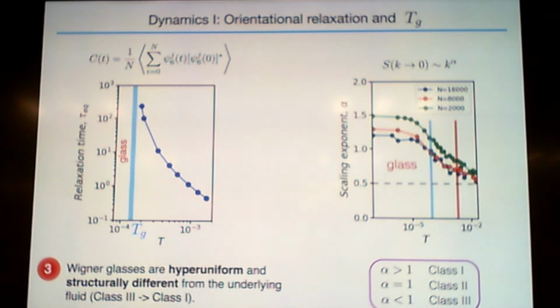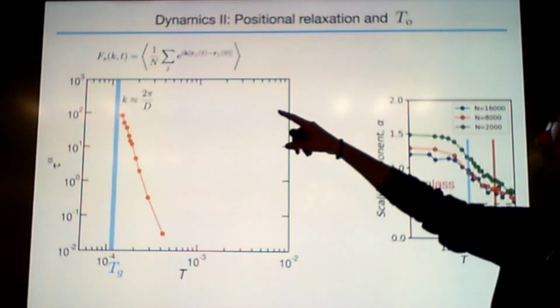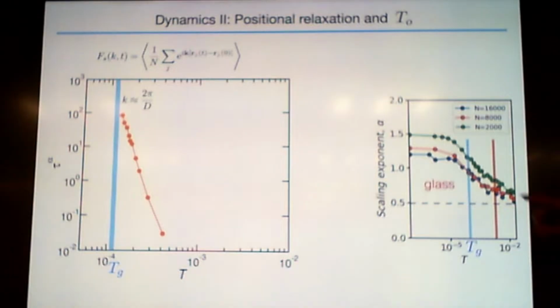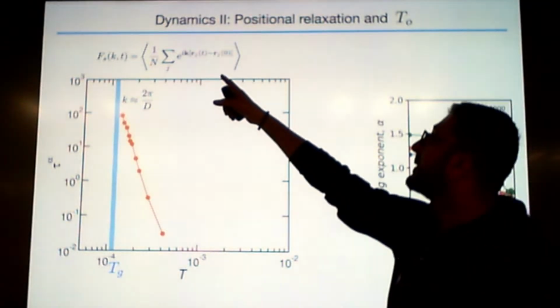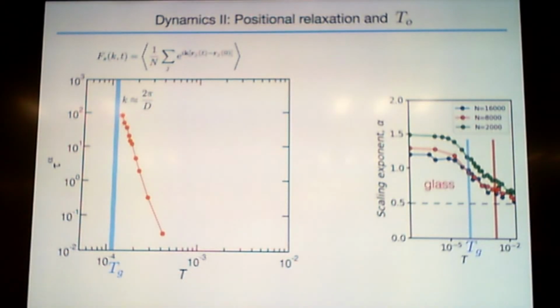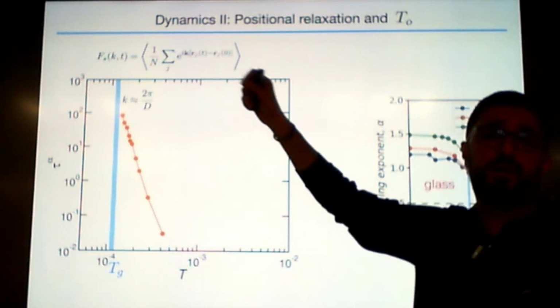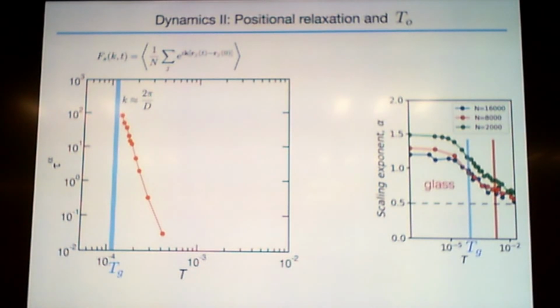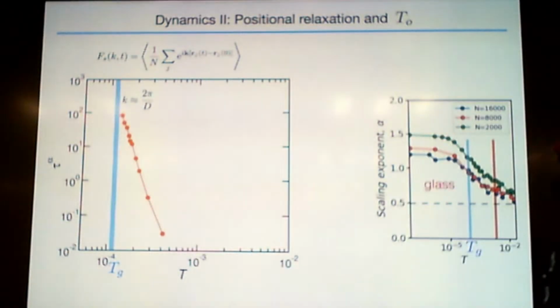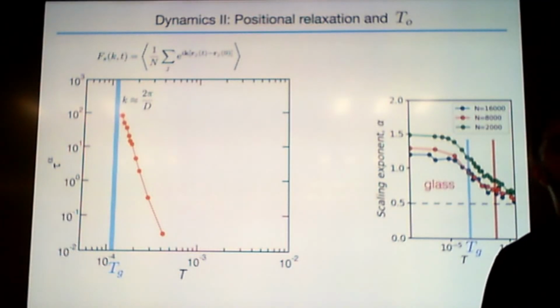Well, you may ask, okay, this is only the orientational relaxation, but we have also looked at the self part of the intermediate scattering function, which measures the positional correlations of particles, not their orientational, but the positional. You keep track of the particle at time 0, and then you measure the correlations, and it turns out that it coincides. Actually, that's the classical way people define a relaxation time, and what a glass transition temperature means, typically. If you wait longer, we don't know what will happen, but we believe it will go up. It will diverge. So that's the critical point. We cannot say at the moment it is a glass temperature, but we say that at least within our simulation time, these guys stop equilibrating.